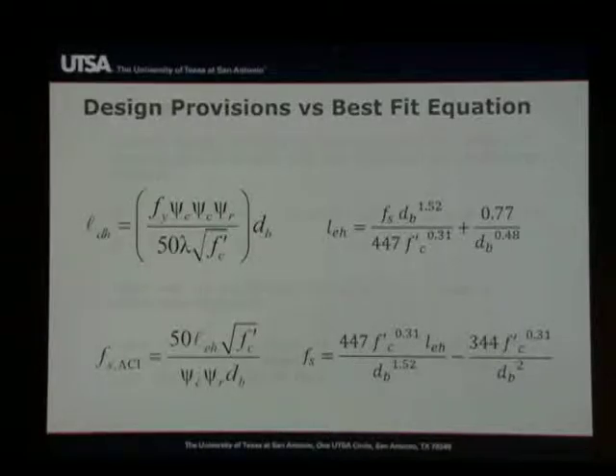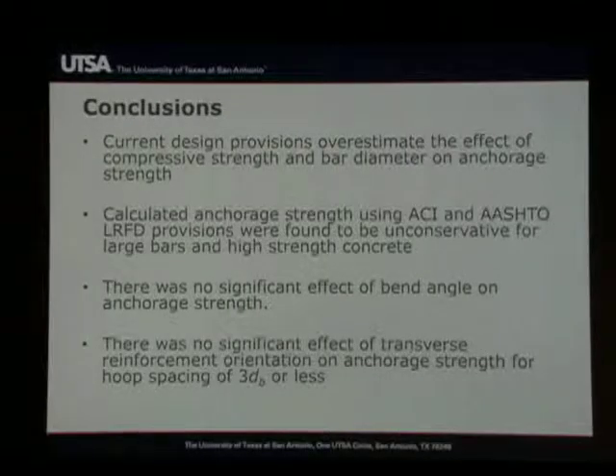All right, so to finalize, I have one slide on conclusions. The main concern of this exercise is that we're currently overestimating the effects of compressive strength and bar diameter when we calculate anchorage strength. This is, I think, of most concern for number 11 bars. And if you compound the fact that you are throwing in high strength reinforcement, you're putting an immense amount of force in a bar on a very brittle failure mode, and we're having the least reliability on the bars that are most sensitive.